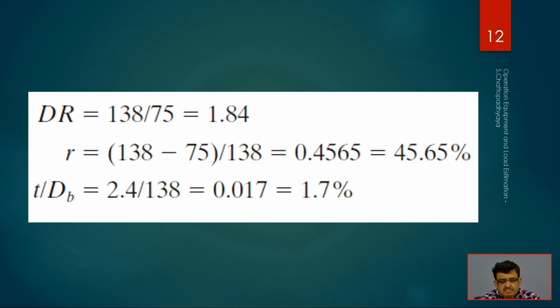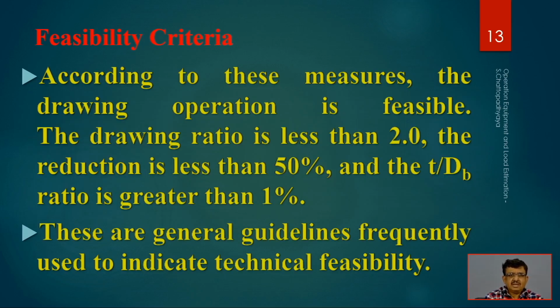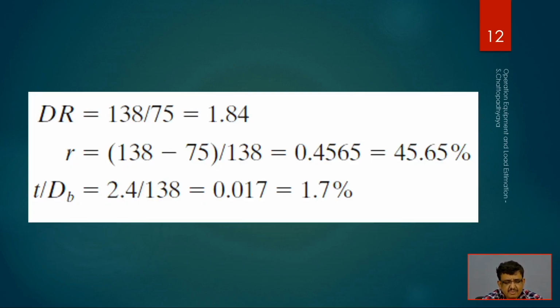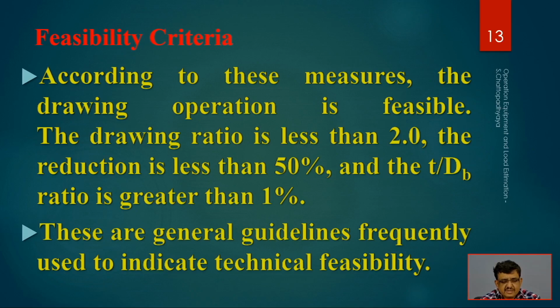On the basis of this information, we have to find out whether the drawability is feasible or not. So according to these typical measures, the drawing operation is feasible. Why is it feasible? Because T by DB is more than 1% and the drawing ratio is less than 2. As we found, 138 by 75 is 1.84, and that is less than 2.